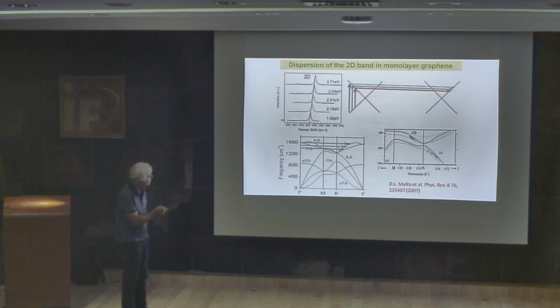But in this case, we have the dispersion of the peak. This is a very unique and interesting phenomenon. And the explanation is like that. If I'm using a red photon, then the electron-hole pair is created at this point. And the phonon that brings the electron from this point to that point is the size of the red arrow. If I had the green photon, then the phonon has a larger wave vector, the green arrow.